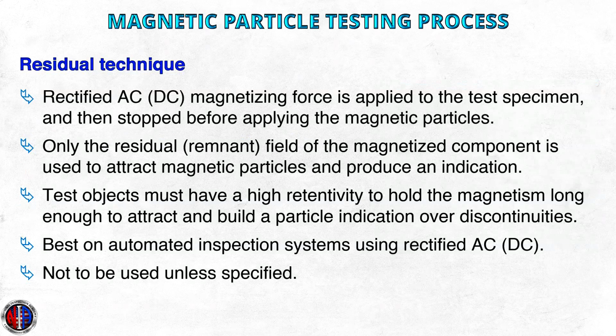The residual technique. The residual magnetization technique is where the rectified AC magnetizing force is applied to the test specimen and then stopped before applying the magnetic particles. Only the residual field of the magnetized component is used to attract magnetic particles and produce an indication.